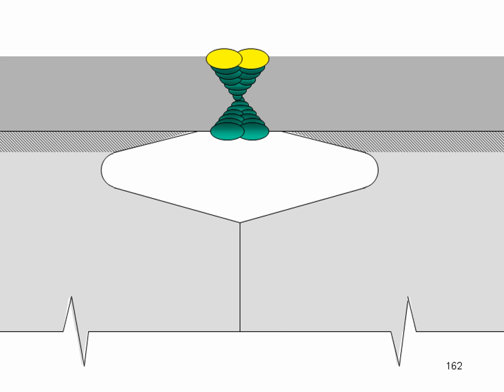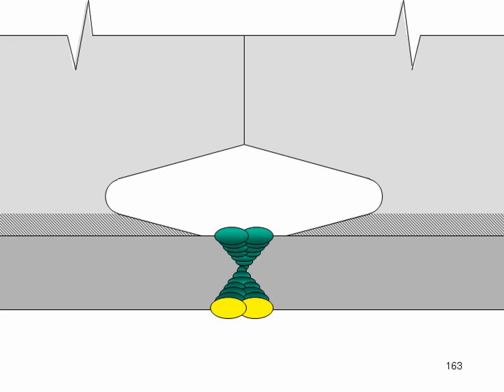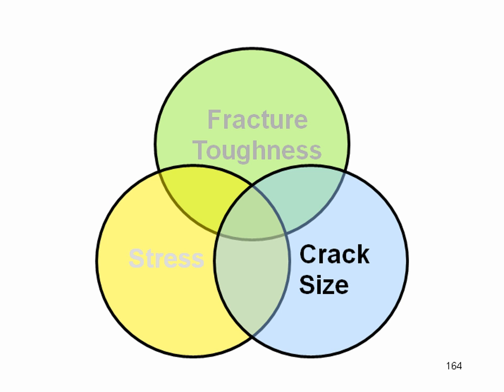I'll go as far as to suggest that maybe you're going to want to do a little overhead welding so that the last final stresses are out away from the region that we know to be somewhat problematic. Now the third thing on our circle was the crack size. And for fracture mechanics, the best thing we can do is make the crack size 0. Get rid of the crack.